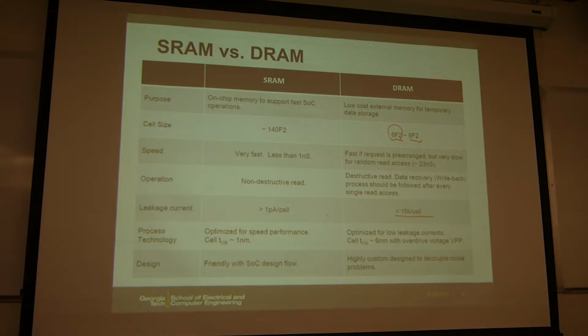So this is a different manufacturing process, different device structure. Even the foundry, I mean the manufacturer, will be different. The DRAM transistor is engineered for very low leakage to maintain the DRAM state. This is like 1 femtoamp per cell. This is very small. For example, one difference you can notice between the SRAM transistor and DRAM transistor is the gate oxide thickness. SRAM uses a logic transistor, and the oxide thickness is probably like 1 nanometer if you use silicon dioxide.